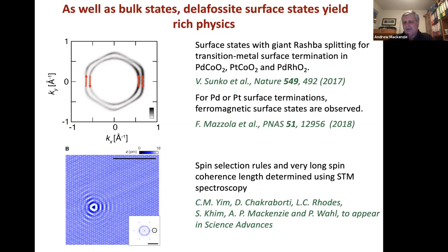And actually, again, to be honest about the photoemission, the question is would you be able then to FIB isolate the area that gave you this Rashba state? Well, with a lot of work, but the way you find it is you scan across the surface forever until you've got a bit which is big enough to give you a single response over the diameter of your beam. Most of the time in the real experiments, they were seeing spectra which were hybrids of cobalt termination and platinum or palladium termination, and just getting all the information at once, which isn't so pretty for the pictures in your paper. But that tells you that this is a very uncontrolled process. You're ripping the thing apart. And not only would you be getting the equivalent of facets, the way the different subsurfaces terminate isn't always the same.